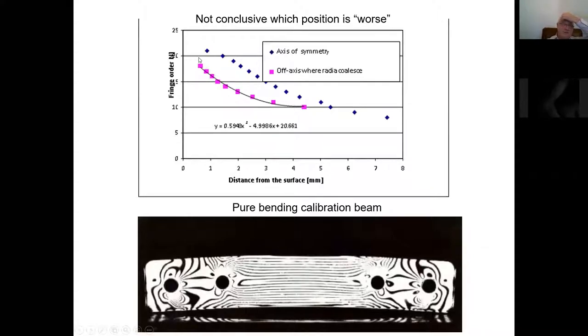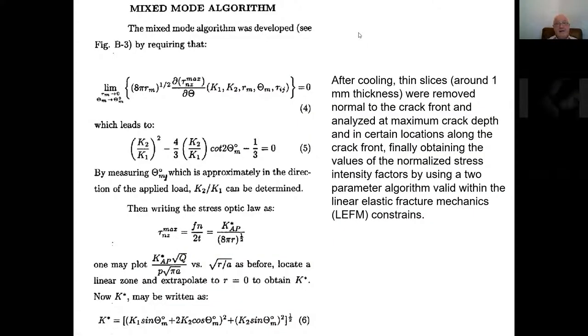So essentially, what was noticed in reality, cracks emanating from both locations, is correct. And on the other hand, for each test, I also wanted to mention, we did calibration. So we established the fringe order by having pure bending, as you know, and measuring the photoelastic constant. Now, of course, depending on the crack growth, you can have mixed mode, especially if it is off-axis. You cut thin slices about 1 millimeter thick around the crack front, normal to the crack front, and then you use the algorithm of this type if it is mixed mode. As I already mentioned, you are looking for this normalized apparent stress intensity factor. Here you have the internal pressure, here you have the crack length, and here you have some correction.